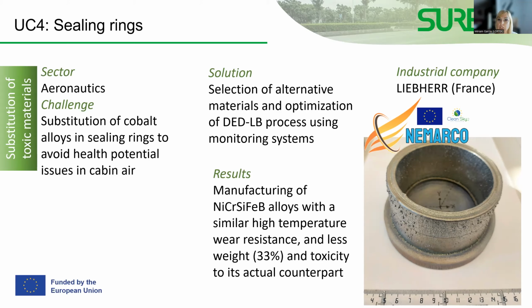So we selected some alternative materials and optimized. In this case, it's a laser-based DED process. We're using powder, using different monitoring systems. So we were able to manufacture these solid sealing rings that you can see in the picture, using nickel alloys, having almost practically the same performance as the actual cobalt alloys in terms of high temperature wear resistance. They were lighter as well, and they had less toxicity than these cobalt sealing rings. So Liebherr has found a very good solution, and actually they are going to continue working in this sense in order to try to produce this at higher TRLs.